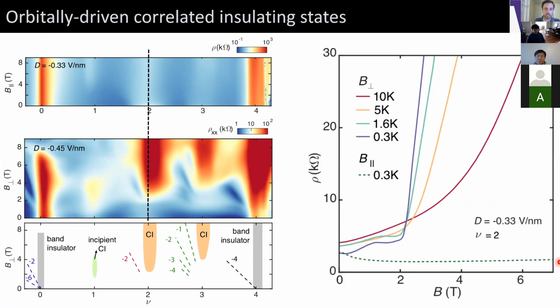So we can get a bit more detail about these states by measuring their field dependence as a function of temperature. So for B parallel, I'm only going to show you base temperature since nothing much happens. It's basically flat. But for B perpendicular, we see this very abrupt change from nearly flat magnetoresistance to very, very strongly diverging magnetoresistance in high field.